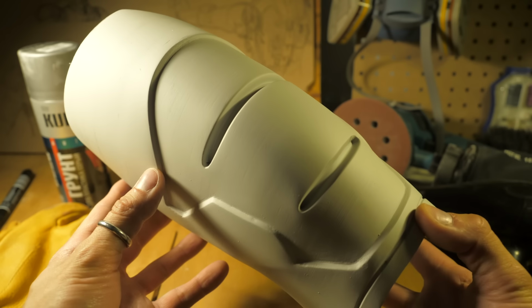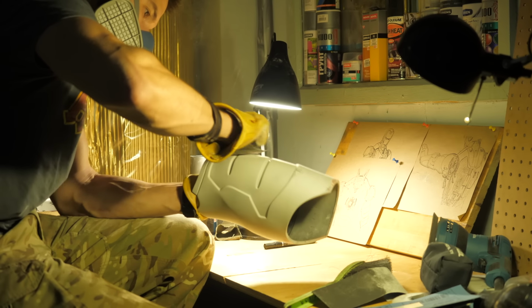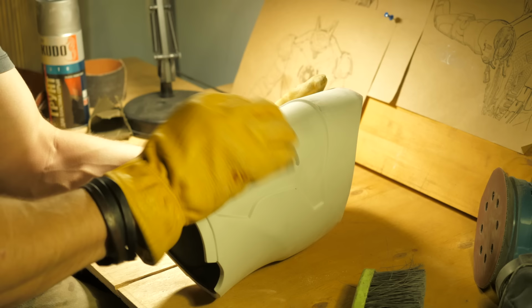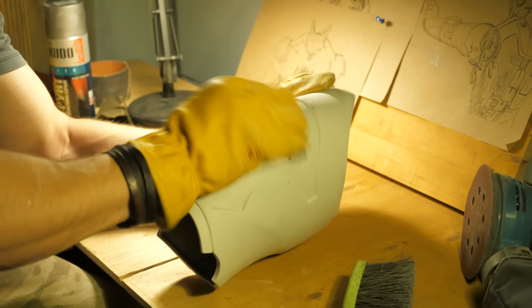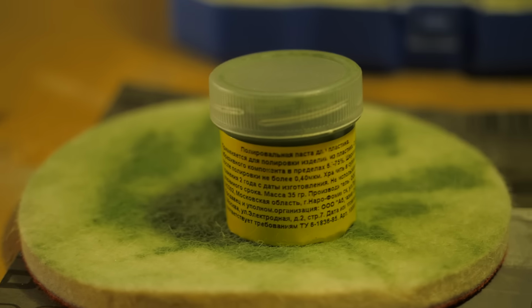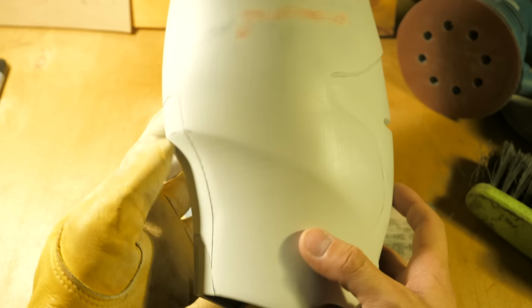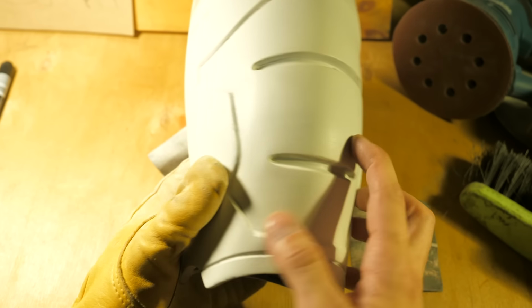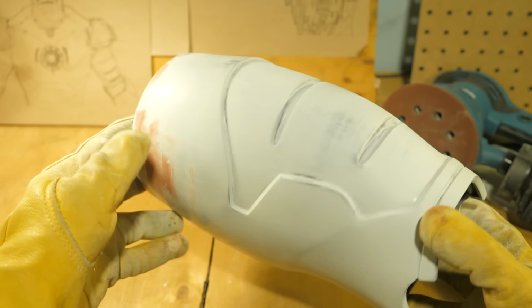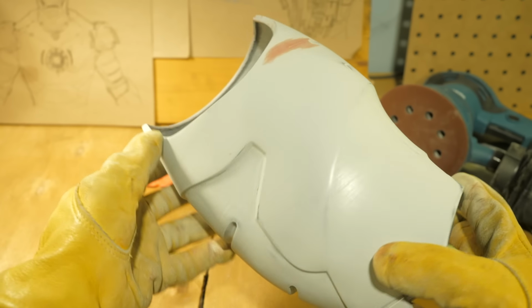When the spray primer dries, proceed to finishing. I do it by hand using 1000 grit paper, then 2000 grit, and then a felt pad with a plastic polishing paste. So we get a perfectly smooth surface with good adhesion and proceed to painting.